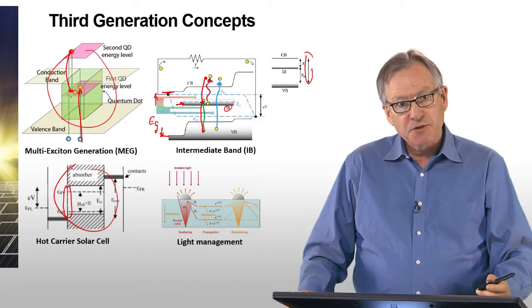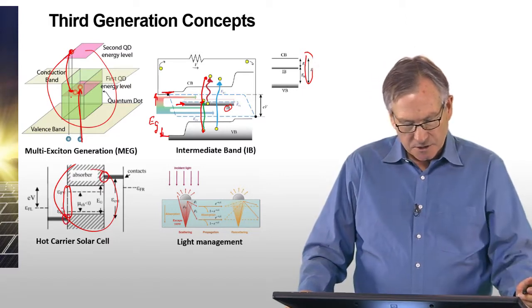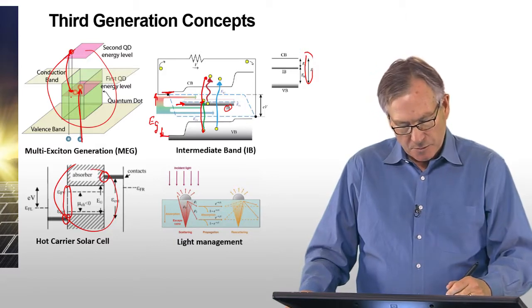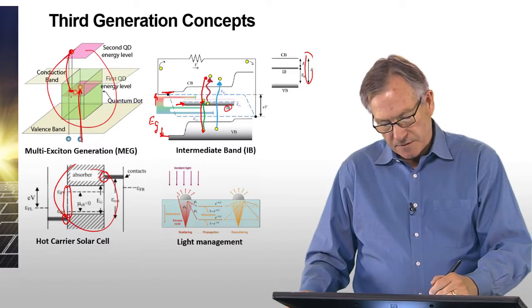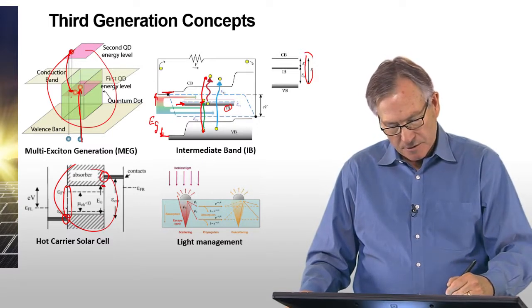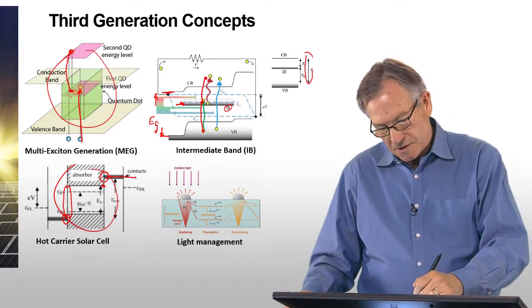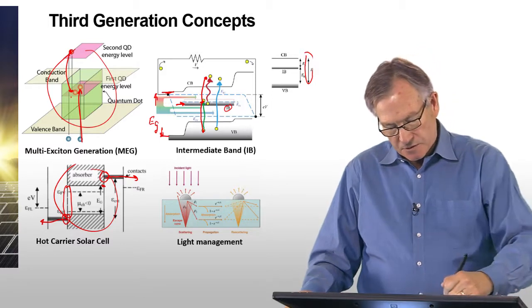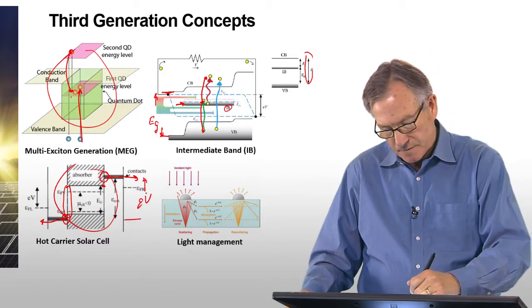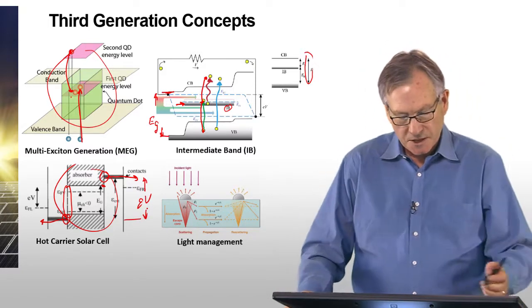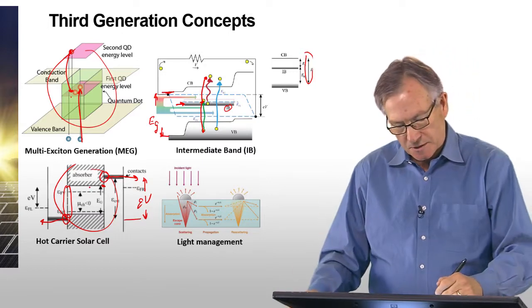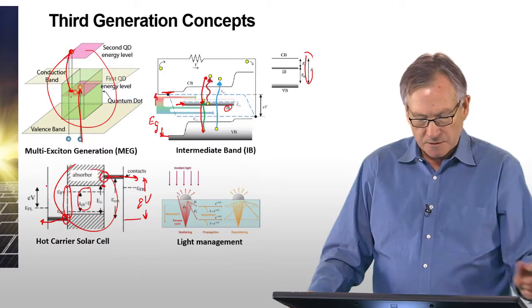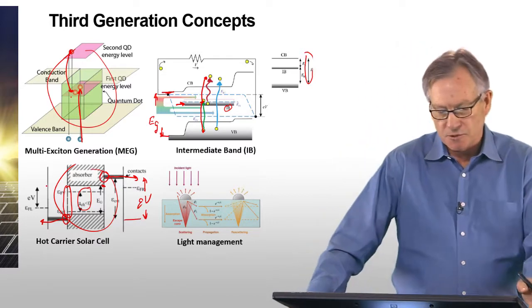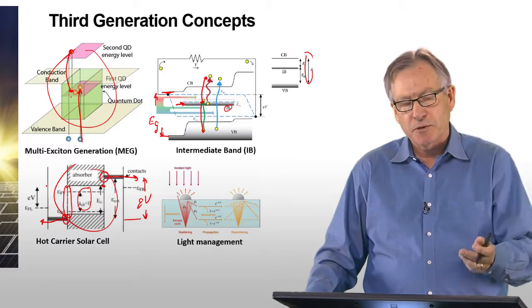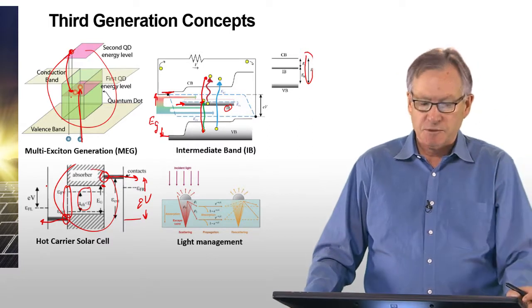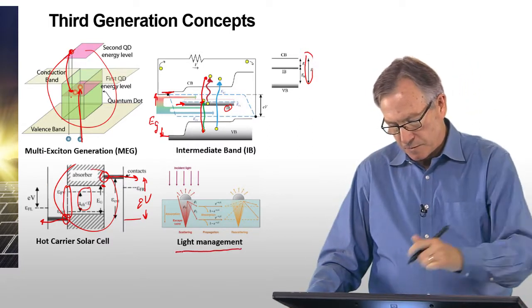And in order to implement this scheme in a useful way, you have to introduce what are called energy selective contacts. There's one contact made to the electron gas, there's another one made to the hole gas, and the energy of this energy selective contact is above that of the energy gap of the absorber. So electrons are harvested out of the contacts at this energy, and therefore the voltage at which you produce electricity is due to the difference in energy of these energy selective contacts, but you harvest electrons at this much smaller gap energy. And this scheme of a hot carrier solar cell also can reach, theoretically, the thermodynamic maximum conversion efficiency on the order of 86%.